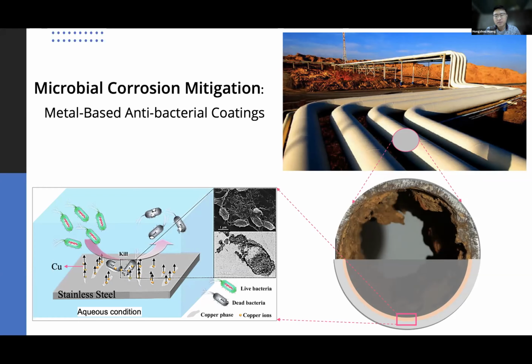One of the areas that are greatly impacted by the microbial corrosion is the pipeline system in oil and gas industry, as shown by the first figure. Due to the unique geometry of the tube, both the outside and inside of the tube could suffer from the corrosion damage. In our project, we mainly focus on the internal corrosion because it is more difficult to detect and prevent, which makes it more dangerous and risky to some degree.